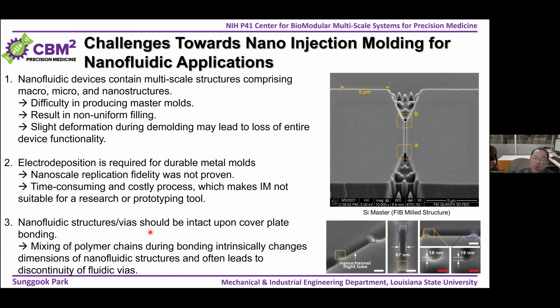So now, what we are doing in our center, this is one of the typical device platforms that we are working on. Here the scale bar is 5 micron. Here we have the microchannels, and then here we have the nanochannel. If you look at the end of the nanochannel, on both sides we have a small dip, and we call this an in-plane nanopore. The depth of the nanopore is less than around 20 nanometers. Once you put a cover plate on top of that using thermal fusion bonding, the effective diameter of this in-plane nanopore becomes less than 10 nanometers. So this is the typical device we are using.